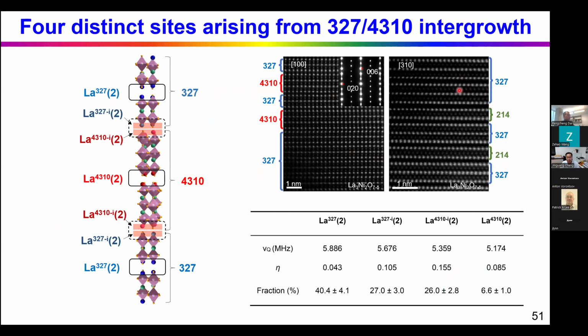So based on the TEM result, we proposed such a structure model. There's the intergrowth between the bilayer and trilayer. If you look at the lanthanum 2 site, this intergrowth will create 4 distinct lanthanum 2 sites. In addition to the lanthanum 2 at the bilayer and trilayer, at the interface you will create additional sites, and they should be located in between these two. So from the frequency, we also found they should have the same area. From the fitting of this peak, we found they have similar area. So this further confirms this picture.